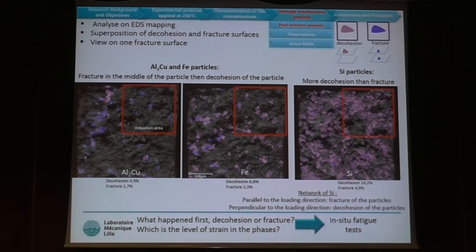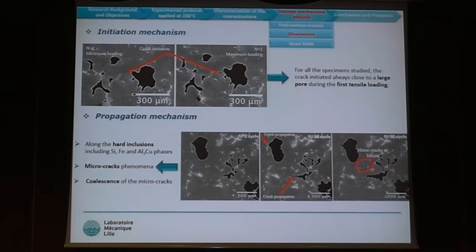But from this post-mortem analysis, we cannot know if decohesion or fracture happens first, and we don't know the strain level of each particle. So you need to perform in situ fatigue tests. From in situ fatigue tests, we can understand the damage mechanism. So here, the initiation mechanism.